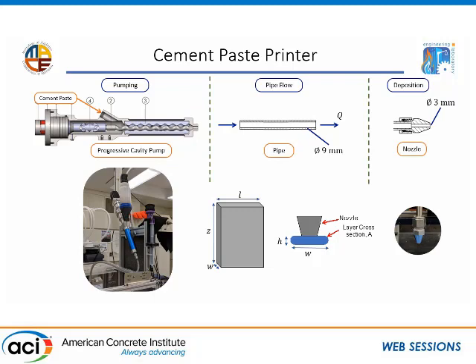We mix our paste prior to adding it to the pump. The material is added into a hopper and then pumped through a hose down to the nozzle. All of this is controlled by the computer using the control hardware on the 3D printer, and we generate the G-code commands using conventional slicing software. The structure we're trying to print is a tall, thin structure — intentionally unstable — so we can see how many filaments we can stack before we get a problem. The filament cross-section geometry is an elongated oval or rectangle with semicircles on the ends.